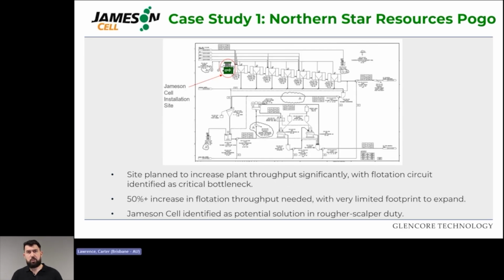The reason for the Jameson Cell installation is the site was planning to significantly increase their throughput, and the flotation circuit was identified as a critical bottleneck. They required a 50% plus increase in flotation throughput, but they had very limited footprint to expand that existing circuit. So they essentially needed something to debottleneck the circuit without taking up much space. And so the Jameson Cell was identified as a potential solution in a rougher scalper duty.